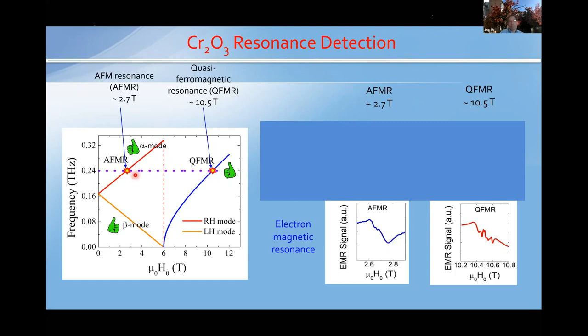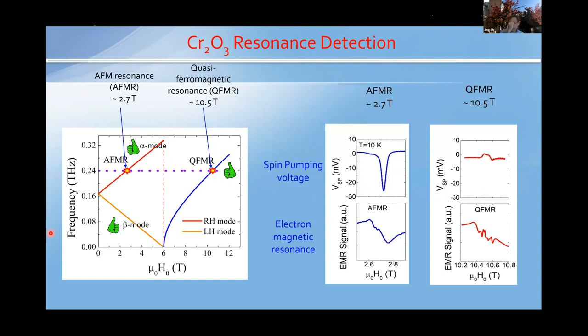Okay, these are probably the two resonances we expected to see in the chromia. However, if we connect to the electric circuit using heavy metal, we see a much sharper and much larger signal compared to this electromagnetic resonance signal. Especially at the antiferromagnetic resonance, this is a very nice sharp peak. For the quasi-ferromagnetic resonance, the line shape is a little more complex. It doesn't look like a single peak, but it is clearly visible compared to the off resonance response. So it stands out.